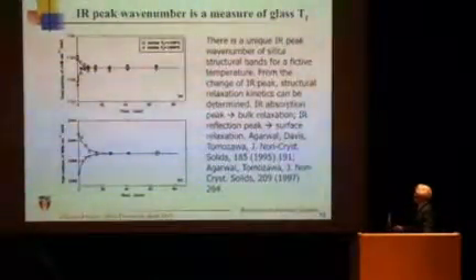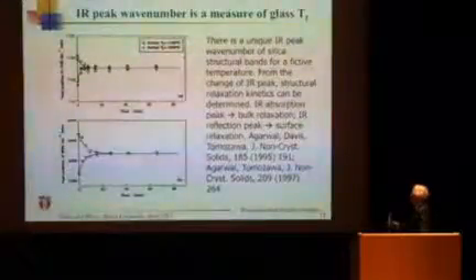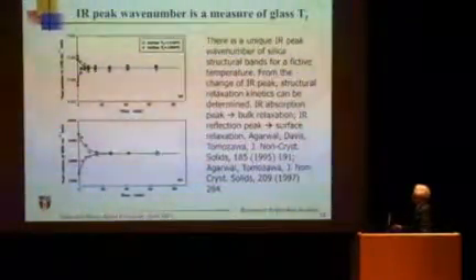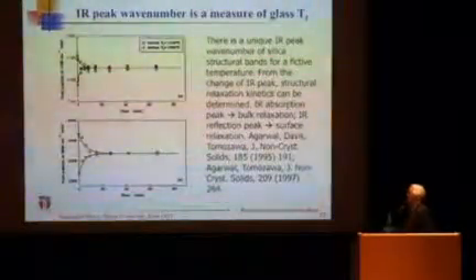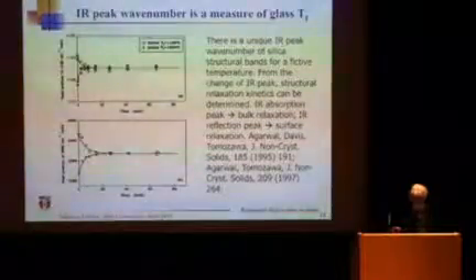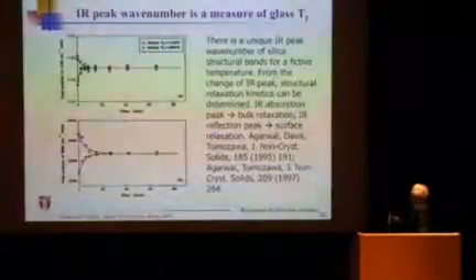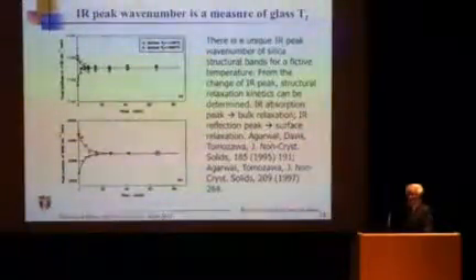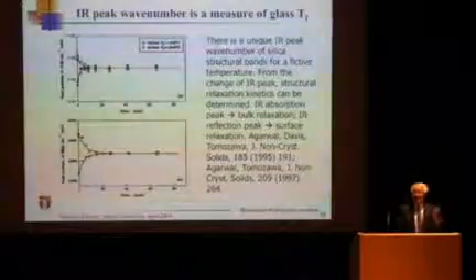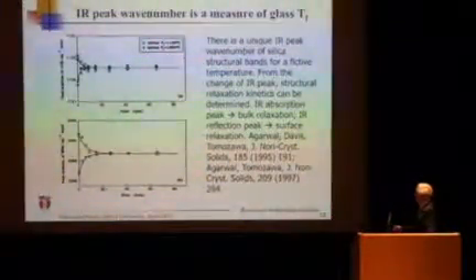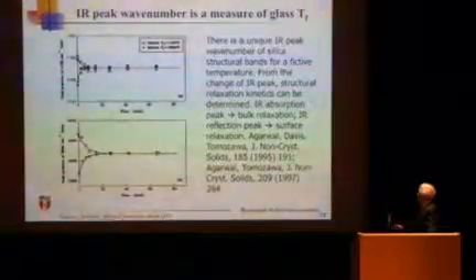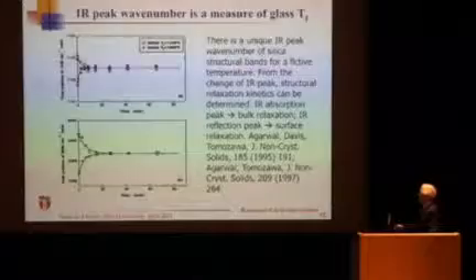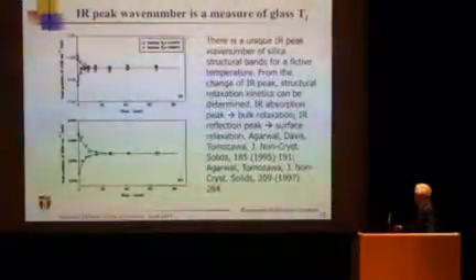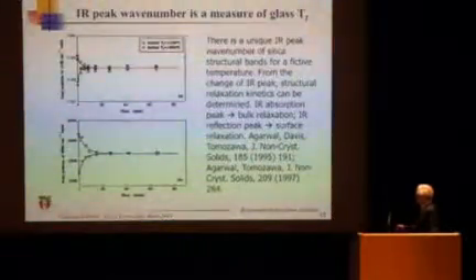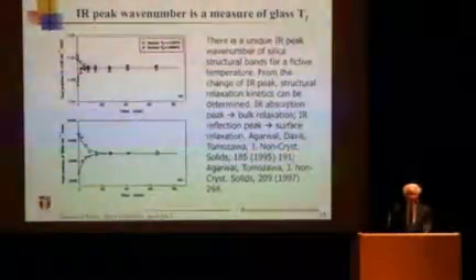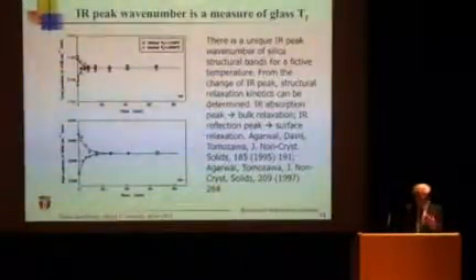From the peak position of infrared, as I mentioned earlier, we found that the infrared structural band peak changed with heat treatment time and temperature. In these figures, we first held the silica glass at 1100 or 1300 for a long time until it reached metastable equilibrium, then rapidly cooled. So the fictive temperature of the initial glasses was 1300 and 1100. Then both glasses were heat treated at 1200 degrees. The peak approaches the same value. From this, the student suggested that the position of the peak is a measure of fictive temperature. This is one of the quickest ways to measure fictive temperature.